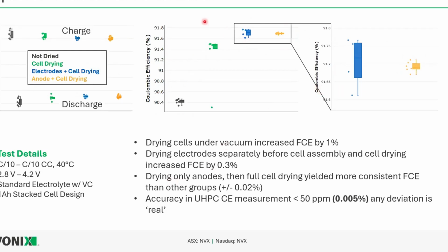So using UHPC for formation, we're really able to see CE measurements accurate to less than 50 ppm. So these deviations that we're looking at here, even though these are really huge blown up scales of only a fraction of a percent, these are real differences that we can measure with UHPC, which is why we do some of these formation measurements on UHPC and see these differences very quickly and accurately.